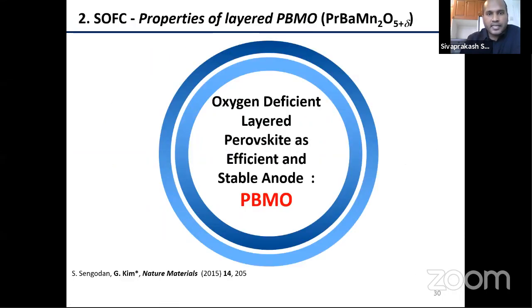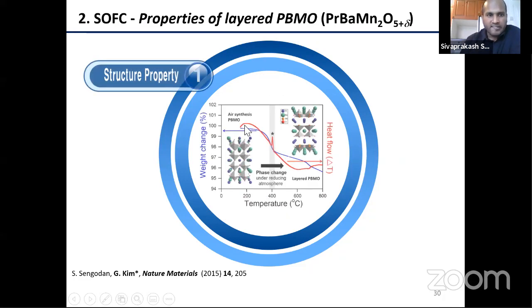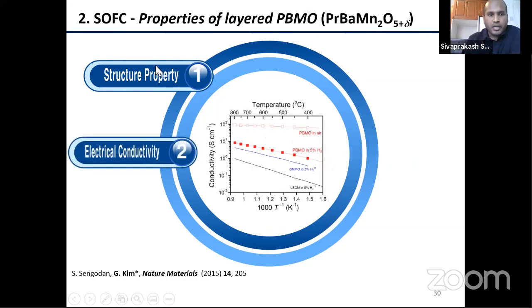Based on these requirements, I have developed a new anode material, praseodymium barium manganese oxide, as an alternative anode material for solid oxide fuel cells. It shows very good structural properties and high electrical conductivity, about 10 Siemens per centimeter in 5% hydrogen.